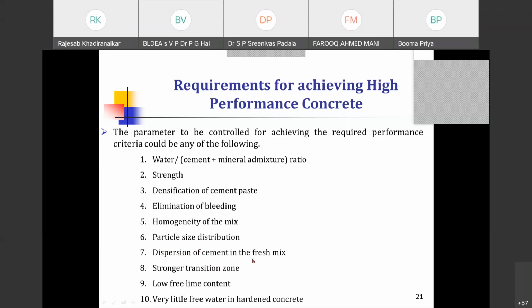Dispersion of cement in the fresh mix. Now we are adding superplasticizer, so dispersion is better. Then a stronger transition zone, as I said, is very critical. So your transition zone is improved, and there is low free lime. Whatever free lime is there is consumed by the mineral admixtures that we are adding, so there is no issue of free lime. It will definitely have low free lime compared to conventional concrete, and very little free water in the hardened concrete, because the water that we are using is very low.